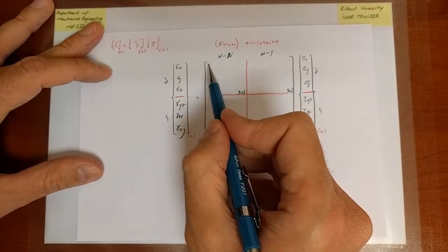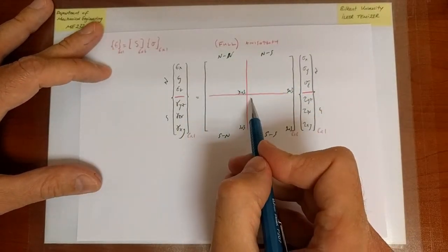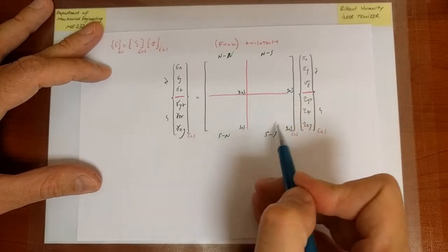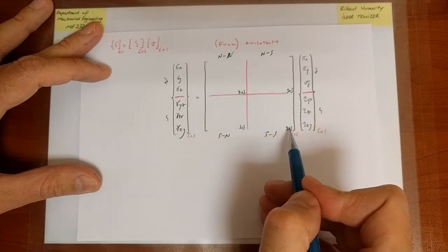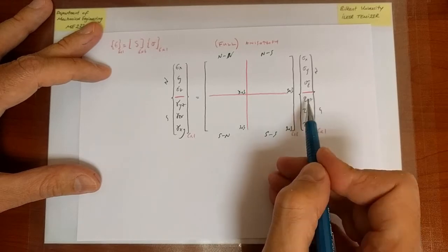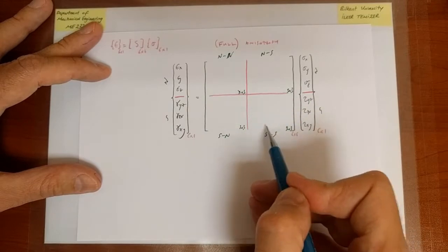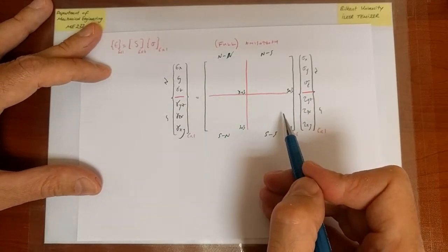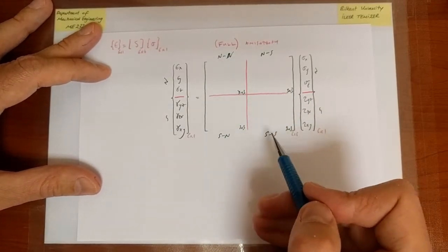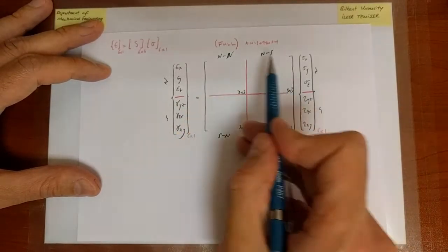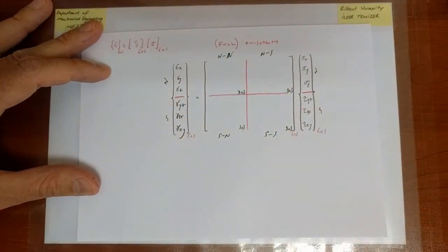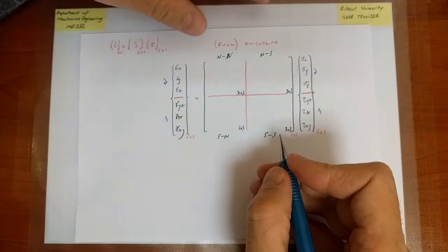And in general, for the case of isotropy, for instance, you've seen that this subblock, this submatrix, was diagonal. In general, I'm going to discard also the notion that only tau yz, say, influences gamma yz. So off-diagonal components of this submatrix are also going to be admitted as being possibly non-zero. So in other words, I'm going to write the full 6 by 6 matrix. So let's go ahead and do that.